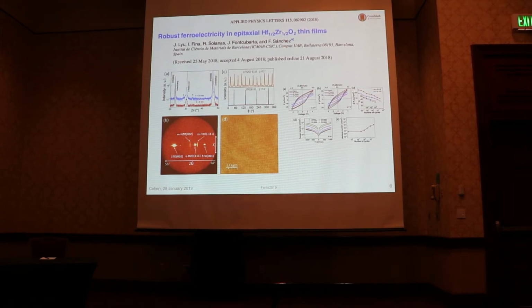So some very nice thin films were grown epitaxially in 50-50 hafnia zirconia, and this just shows some of their films, data, and some of their ferroelectric properties that were measured. And again, it's getting better. People are measuring reasonable polarizations and reasonably reproducible results for given growth conditions.